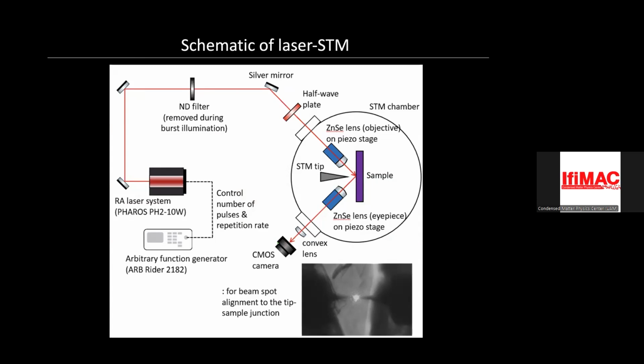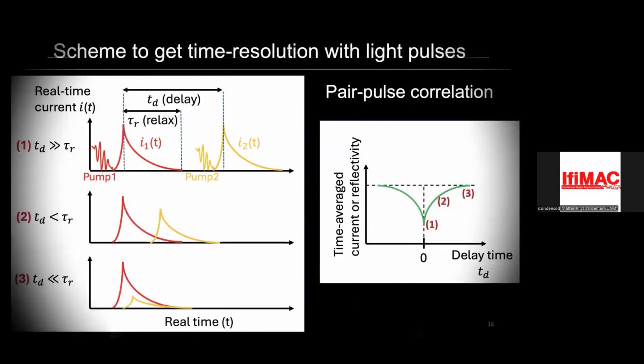And so here you can see the tip, you can see the light, and you can see the reflection of the tip. The important thing here is, imagine you have a tip and you have this laser spot, and the laser spot is only 10 microns, and you can miss it, right? You can miss the area where the laser spot is illuminating your sample. So you need to be able to position the tip on top of the light. This used to be a big problem, but because we can see, it makes life a lot easier. We can actually position the tip right on top of the spot.